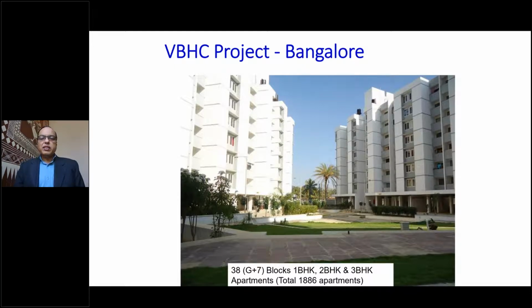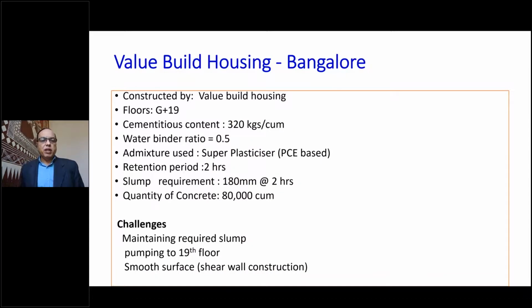Now, what was the difference here? What was the additional thing that was done here? These are the details of this. Look at the concrete that was used. The cementitious content was 320 kg per meter cube. Water binder ratio was 0.5, and the PCE based admixture super plasticizer was used. And the retention period, that is the slump retention period, was 2 hours. Slump requirement was 180 millimeters till 2 hours.